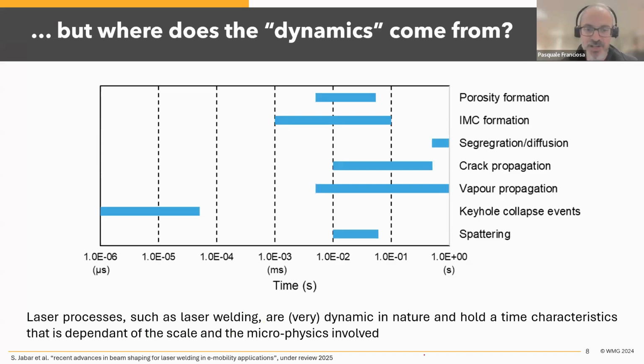If you look at the time scale, we are talking in seconds. Diffusion can take seconds, even minutes, sometimes even hours, but we go down to microseconds, so very small scales. All those physics are happening within the time scale you see on the slide. So there is a clear dynamics, and the whole idea of using dynamic beam shaping is to influence those physics as they are happening in such a way that we have a tailored response of the material properties in the end, once the weld material is resolidified.